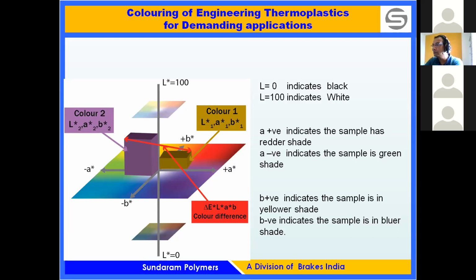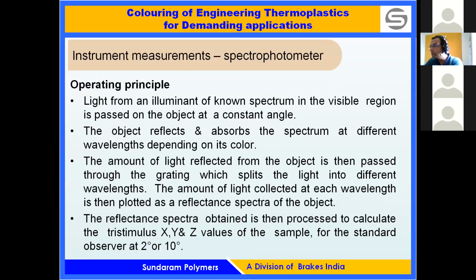The operating principle of instrument measurement is that light from an illuminant of known spectrum in the visible region is passed on the object at a constant angle. The object reflects and absorbs the spectrum at different wavelengths depending on its color. The light reflected from the object is then passed through a grating, which splits it into different wavelengths. Reflectance is then plotted as the reflectance spectrum of the object. The reflectance spectra obtained is then processed to calculate the tristimulus XYZ values of the sample for the standard observer at 2 degrees and/or 10 degrees, depending on the requirements.